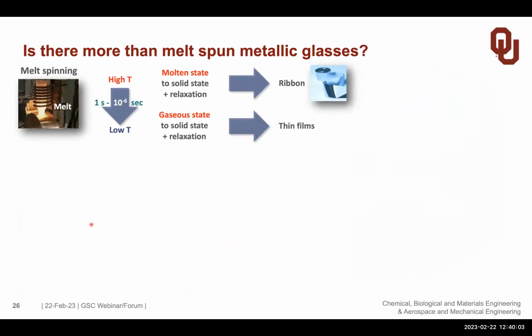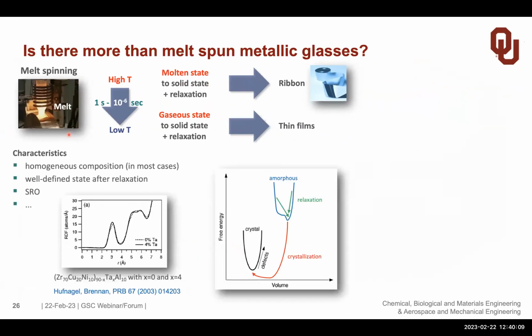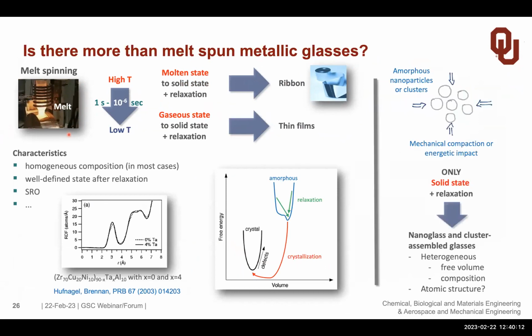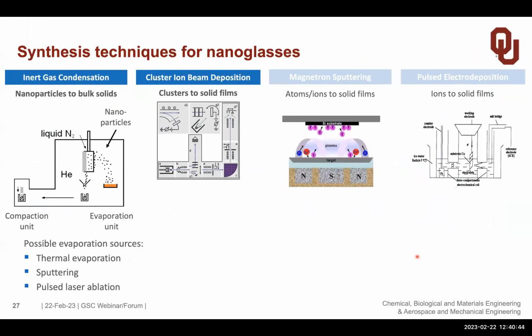So now I have told you that we can prepare these metallic glasses by melt spinning, by rapid quenching. And we have come up with a different approach, which I would like to share with you. This is a room temperature process where we take nanoparticles, which are amorphous, and we compact them. In doing that, we do not have the involvement of a high temperature, but everything is done at room temperature, and we form a nanoglass in a way which we have found to be a heterogeneous metallic glass, and it also has new properties. There are other techniques, which I will go over, for how to prepare that.